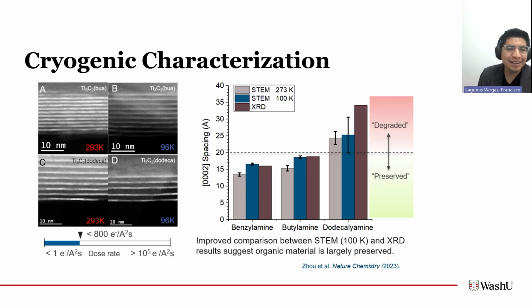So nonetheless, I went ahead and did the analysis for these materials using cryogenic STEM. And here's a summary of what we saw. In gray, I have the original measurements we did with traditional STEM at room temperature. In this dark red color are the values from our XRD measurement, which we're a little more confident in because the XRD measurement doesn't happen in high vacuum and is less prone to degradation of the material, or less damaging to the material, than STEM.